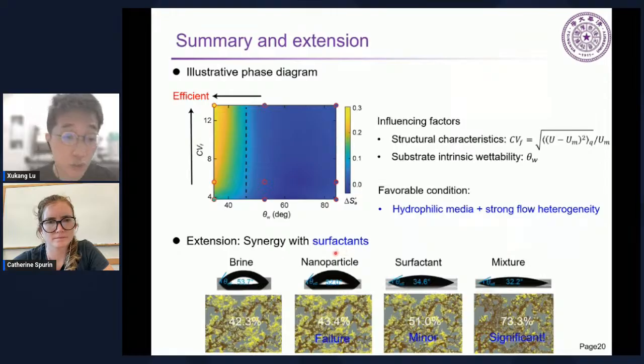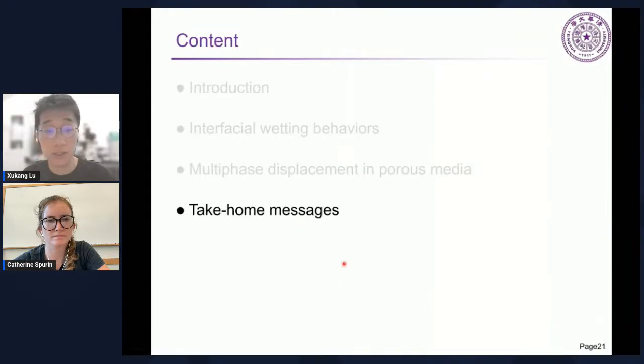And finally, I would like to show a small extension. From this phase diagram, you would say the scenarios for nanoparticles are very limited, because when the surface is hydrophobic, it seems that they cannot play their roles. But we can also combine it with some other methods, like chemical-based methods. We can just use some surfactants to modify the surface property to make it satisfy the corner flow criteria. And then nanoparticles can further play the structure effects. So here is a demo of this synergistic effect. You can see the mixture system induced a much higher displacement efficiency increment compared to the pure nanoparticle or surfactant systems. So that's basically all the presentation.